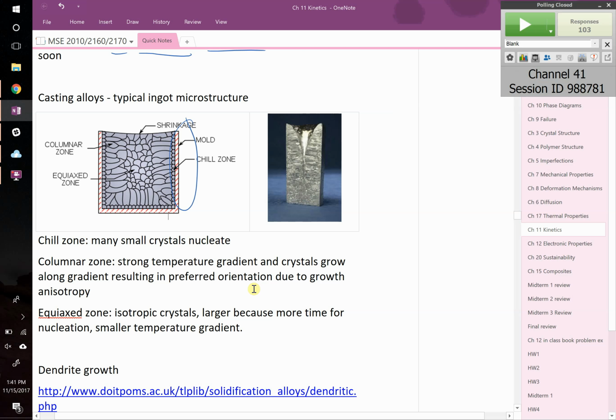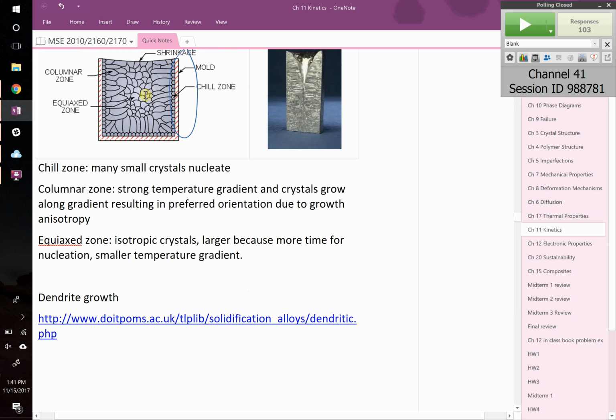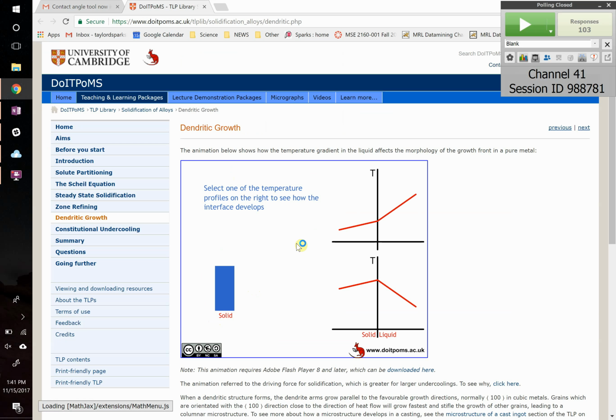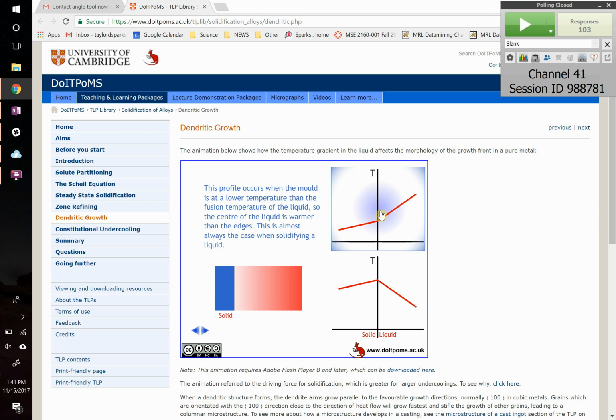Okay, let's keep going. One other thing to know is that this is one type of microstructure. Another very common type of microstructure is called the dendritic structure, and it's pretty cool how it works. So let's show you the two examples. This is from Cambridge. They've got a great little flash tutorial on it. So you've got two scenarios. Here's your first one. On the right-hand side, this is the liquid, this is your alloy. On the left-hand side, this would be like the container, right? As you start to solidify, your solid is going to form near the container. If the temperature of your liquid is much hotter than your container, then something might solidify, but the rest of it is going to catch up. So these perturbations at the surface keep on getting swallowed up, and it's going to look like just the alloy that we just saw.